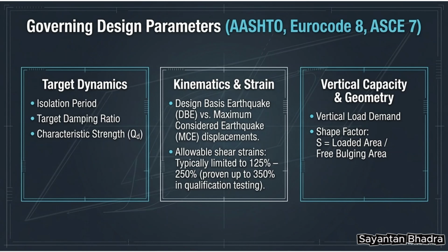LRB design strictly adheres to major international codes through three core parameter sets. Target dynamics focus on matching the required isolation period, target equivalent damping, and characteristic strength Qd. Kinematics and shear strain demands are evaluated under design basis earthquake (DBE) and maximum considered earthquake (MCE) hazards, limiting total shear strains to typical allowable limits of 125 to 250%, validated up to 350% during destructive qualification test.